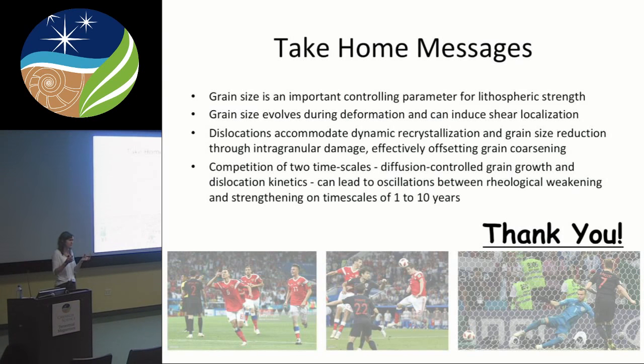The effect of dislocations, the forces associated with the intragranular defects interacting with the forces associated with the grain boundary energy, and the two will matter for the grain size you'll observe at the end and that you'll use to infer the stress for your deforming material. And then I illustrated that there are these different time scales associated with the different physical processes that can potentially lead to some interesting behavior within cycles of strengthening and softening and so forth.